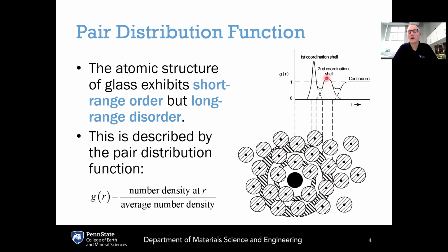Again, because this is above 1, this means that you're more likely to find atoms in this second nearest neighbor regime compared to just a random distribution of atoms in the limit of large distance. But what you'll notice about the second coordination shell is, first of all, it's broader compared to the first coordination shell. The fact that the first coordination shell is so narrow means that the first nearest neighbor distance is actually quite well defined. However, if you go out to the second nearest neighbor, there's a bit more randomness that gets introduced into the structure. And even though the second coordination shell is still greater than 1 here, the fact that this is broader means that the atomic positions for the second nearest neighbor are spread out a bit more. They're less well defined compared to the first nearest neighbor shell.